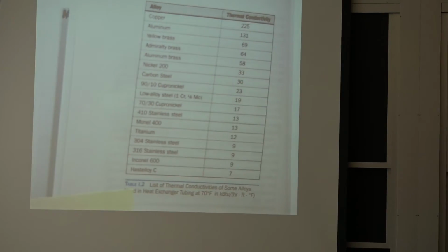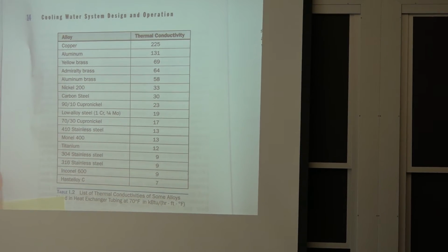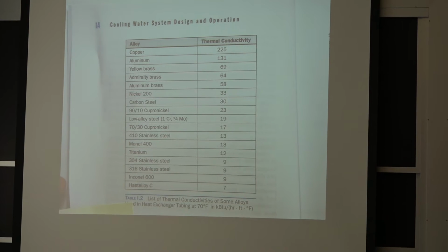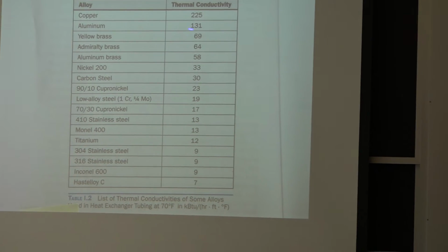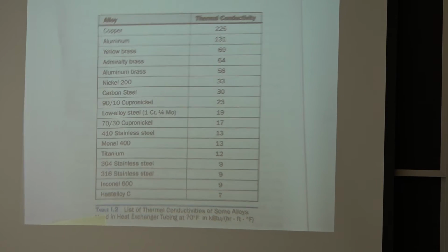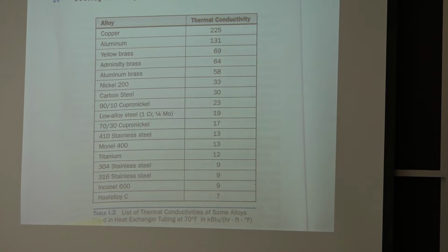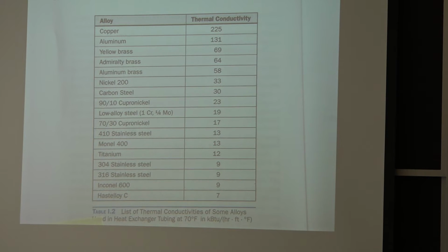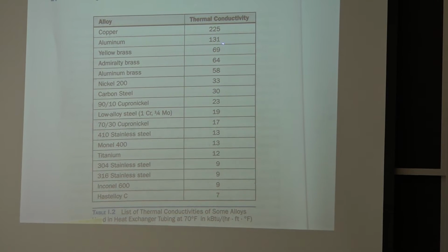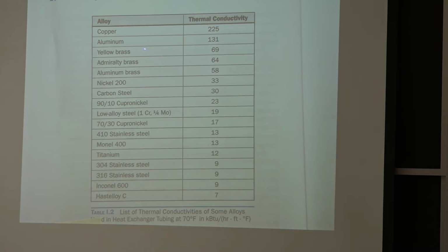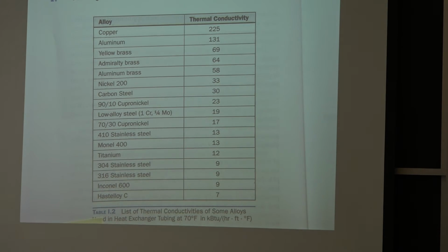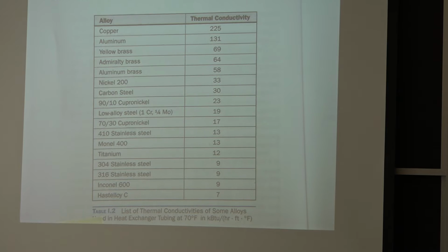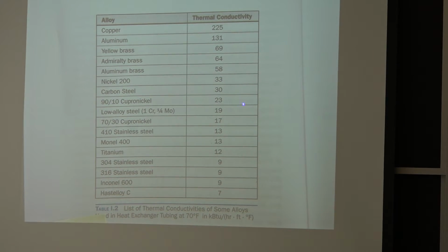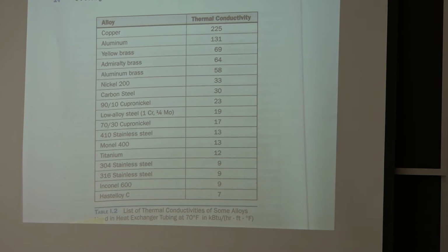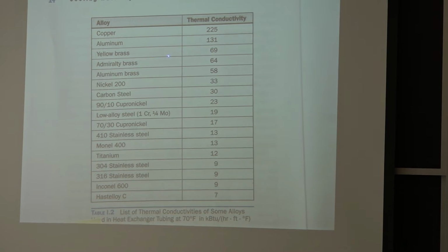We talked about condenser tubes, or I mentioned some things about condenser tubes. And these are some of the materials from the very beginning of the book, some alloys for heat exchanger tubing. Okay, condenser tubes. And so copper's got the best thermal conductivity. You're trying to transfer heat, so you'd love to use copper. And if you got good, really clean water with no solid particles in it, they're going to cause erosion. Copper would be great. Aluminum is good, but it's pretty soft and would erode away. Although aluminum has very good corrosion resistance in sewage. You go down here to the sewage treatment plants here in Boston, all made out of aluminum, okay? Because the pH is somewhere near 7, okay? And aluminum is very good. We'll see why a little bit later.